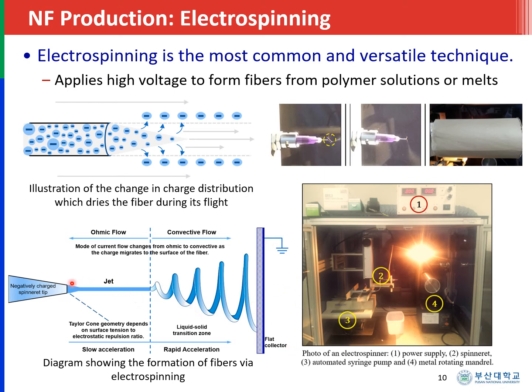One electrode of the voltage source is placed into the solution, and the other is connected to the collector. A droplet of the polymer solution then forms at the tip of the capillary, creating a point known as the Taylor cone. And the geometry of the Taylor cone would depend on the surface tension to electrostatic repulsion ratio. When the electrostatic force overcomes the surface tension of the drop, a charged continuous jet of solution is ejected from the cone.